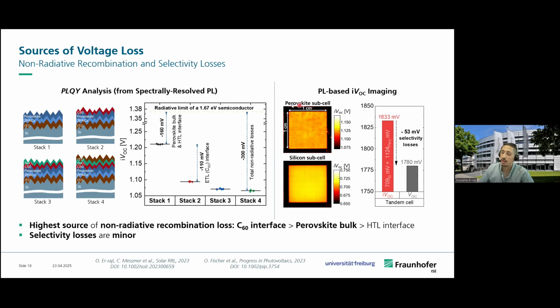In this method, we have our tandem cell, and by using specific laser wavelengths, we can have a subcell selective measurement. So for example, to get an idea of the IVOC in the perovskite subcell from the tandem, we can use a blue laser that will only excite the perovskite subcell, and this gives us an indication of the IVOC in the perovskite subcell. We can do the same in the silicon subcell, and then we get an idea of the IVOC of the whole tandem, and by comparing it to the VOC of our device, we see that the selectivity losses are really minor compared to the total non-radiative recombination losses in the perovskite top cell. So this is what we have to target first in order to have the largest gains in VOC.